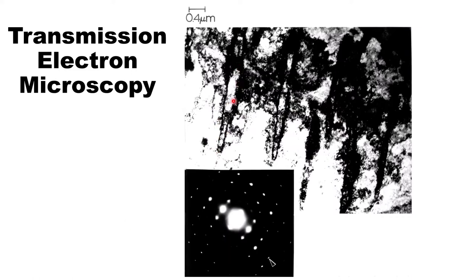The microstructural feature of interest is called microbands — they are dislocation structures. The diffraction pattern here indicates a 15-degree misorientation with the parent lattice, and that's how you identify this as a microband. It's this 15-degree characteristic misorientation angle.